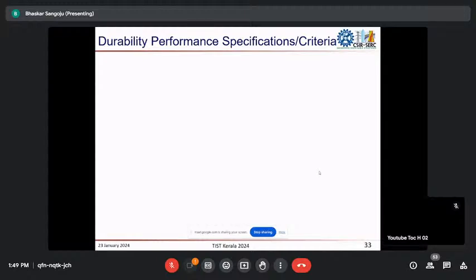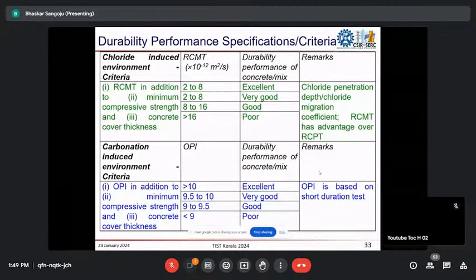So for durability performance specifications, we based on our SERC's experience, as I was telling, a performance criterion is proposed: when a concrete is exposed to a chloride induced environment, RCMT, rapid chloride migration test, in addition to minimum compressive strength and concrete cover thickness. I keep on telling concrete cover thickness is very important because that acts as a barrier and also does not allow the deteriorating agents to enter inside the concrete. Okay. So to ensure that, we are putting two parameters in addition to the evaluation of strength. One is rapid chloride migration evaluation. The other one is adequate concrete cover thickness.